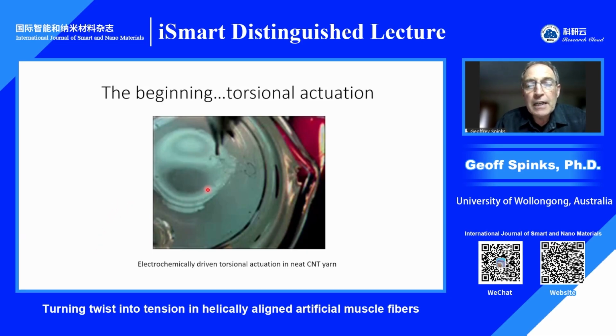And what you're seeing here is a video that he took. This is looking down into a beaker. There's some liquid electrolyte. And then there's this fine thread that you might be able to pick up here, which is a carbon nanotube yarn. It's connected at one end to an electrode. There's a reference electrode and a counter electrode in the beaker. And he's then scanned the voltage to do a cyclic voltammogram test.